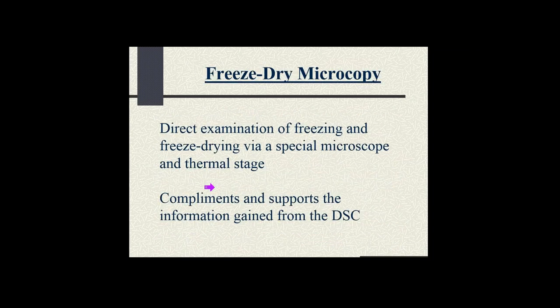Okay, freeze-dry microscopy. So we do the DSC. A sample comes in the lab. We do the DSC. It tells us, number one, what is the thermal event? Is it glass transition? Is it eutectic melt? And what are the critical temperatures that are associated with it? We then go to the microscope. And this, again, what this will tell us is where that sample physically loses structure.